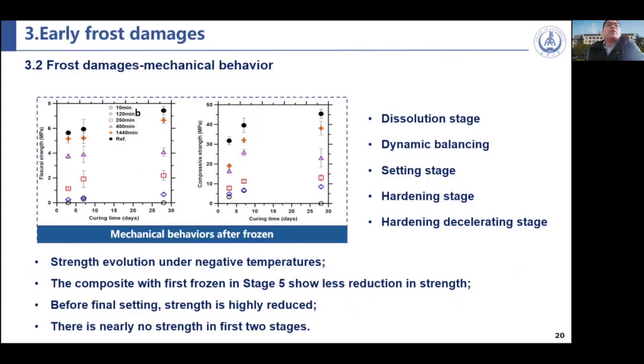And also before the final setting, that is in the first 3 stages, the dissolution stage, the dynamic balancing stage, and the setting stage, the strength is highly reduced, especially for this 4 and this 4 stage. And also there's nearly no strength in the first 2 stages, such as this point and this point, the dissolution stage and the dynamic balancing stage. If the first frost exists in the dissolution stage and the dynamic balancing stage, the structure and the material will be damaged totally.